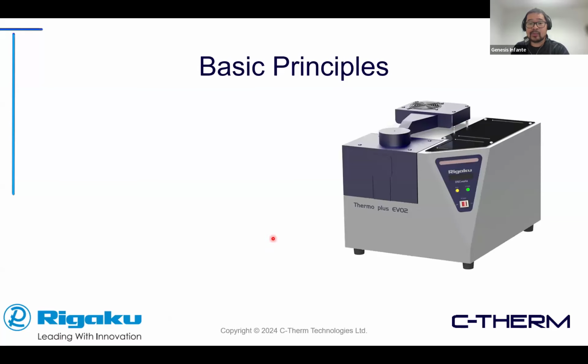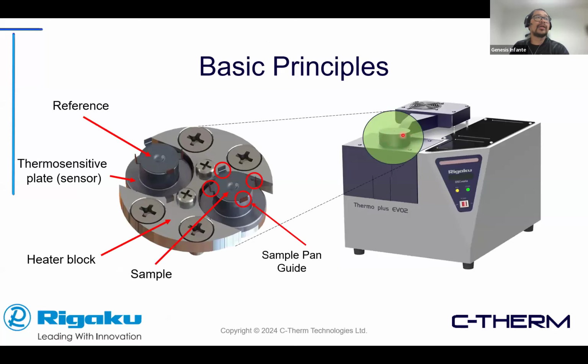On its basic principle, the way that DSC works is that the sample is going to be loaded into this sample test chamber right here, and what this test chamber looks like is something like this, where you have two different locations: a reference material or reference pan, and a sample pan containing the sample test material, which is located on the right side. We're going to have a heater block and a thermosensitive plate for detection. Specifically for this particular DSC, you'll see there is usually something like a claw, part of the design, to secure the pan, to ensure that during the test itself, the pan that contains the sample and the reference doesn't move for one reason or another.